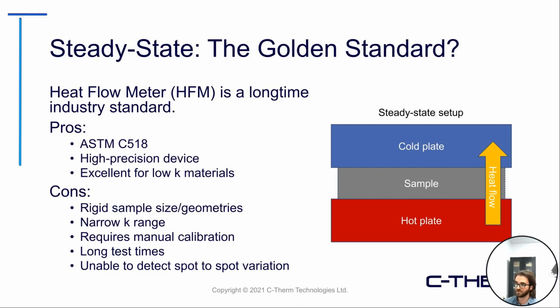Now, Adam did mention earlier the steady state method. Obviously this is widely adopted in the industry as a long-time standard. Steady state heat flow meters really benefit from the use of the ASTM C518 methodology. It's a very high precision device, excellent for those lower conductivity samples. Of course, there are a few drawbacks. Generally there are more rigid sample size requirements and geometries, and longer test times. You are measuring over a much larger area based on the sample requirements, so you lose a little bit of the spot-to-spot variability that may be present in a material. As shown on the right, a steady state setup has a hot plate and a cold plate with your sample in between, and you're measuring the heat flow through that material once it reaches steady state conditions.